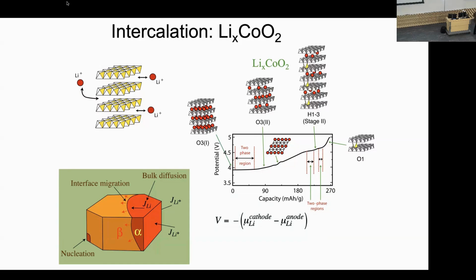And then at 50%, this is where half the lithium ions have been removed. In that case, in these layers, the lithium ions like to order in rows. So you get a row of lithium, row of vacancies. And this is the pattern that emerges in these layers. And that shows up as a little step, a little kink in this voltage curve. And if you couple this with diffraction, so you can simultaneously do an XRD study of this, you see superlattice spots of this ordering showing up exactly where this kink shows up in the voltage.